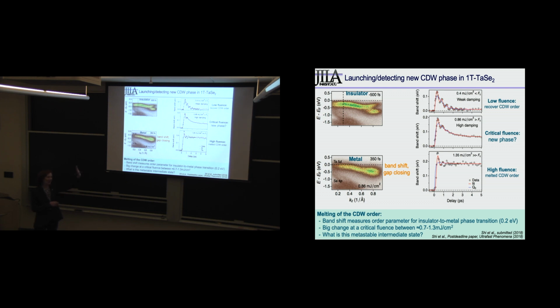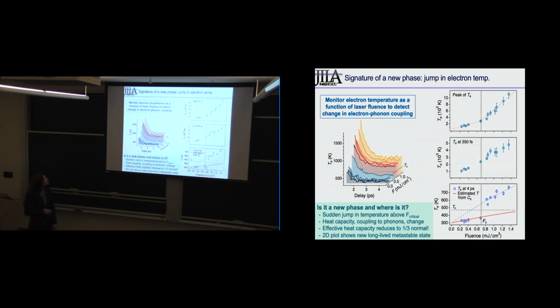So that's not enough for me to claim that's a new phase or anything, but what you can do is measure the electron temperature. So if you measure the electron temperature, what you start to see is normally the slope of the electron temperature versus laser fluence is related to the heat capacity. And what one sees is that at a particular laser fluence, the slope changes. And there's even a jump, and by 4 picoseconds, there's actually a very big jump. And it turns out that jump is big enough that the effective heat capacity must be reducing to 1/3 that of the normal. All that's happening, it's a 2D material. We're not exciting the cross-plane phonons. So that's what's giving rise to that aspect. Or very likely, there isn't a theory, but we think that's what's giving rise.